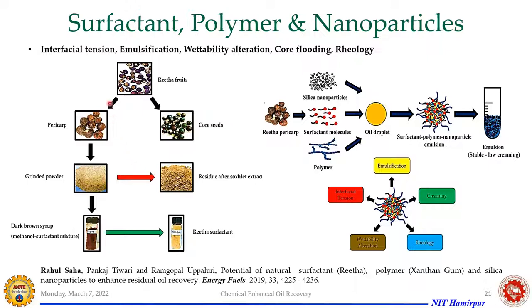So based on that, we've taken Reetha fruits. This is available; I've collected this from the Guwahati, Assam local market. I've taken the seeds and extracted the pericarp, and these are the core seeds. This pericarp is ground into a powder form, and then it is extracted by solvent. In this solvent extraction, a syrup is formed, which is then exposed to a rotary evaporator to dry the sample, and we got this final surfactant, which is the Reetha surfactant derived from the Reetha fruits.